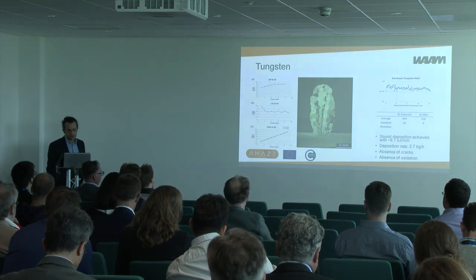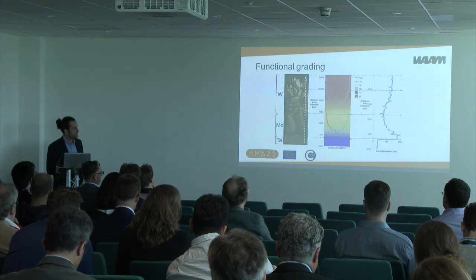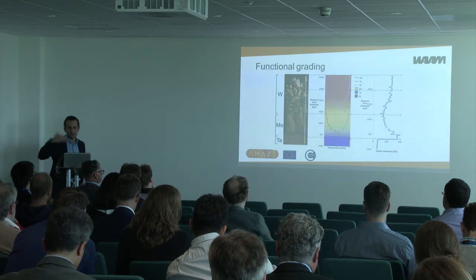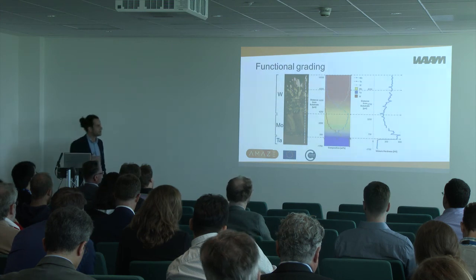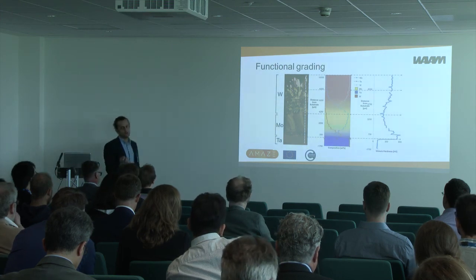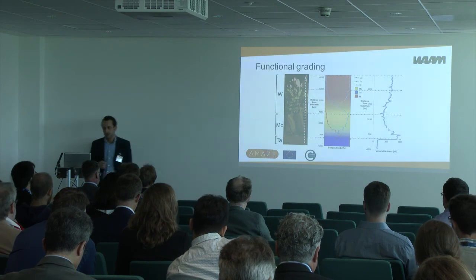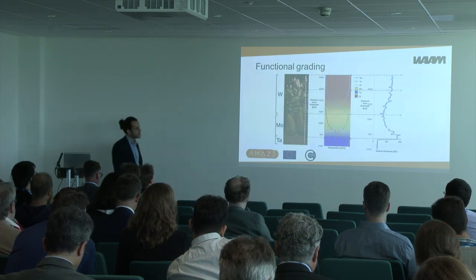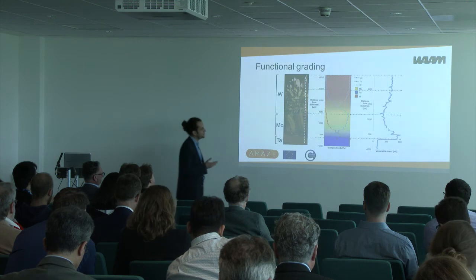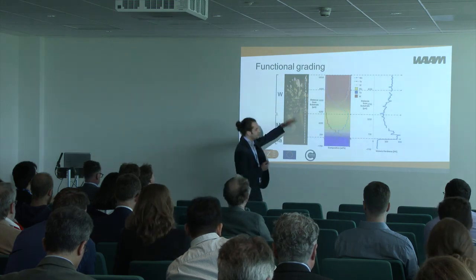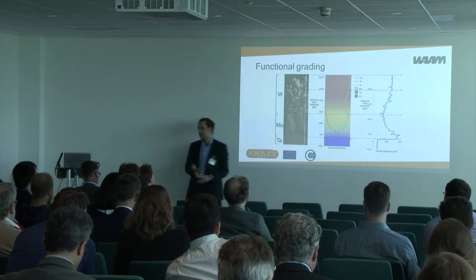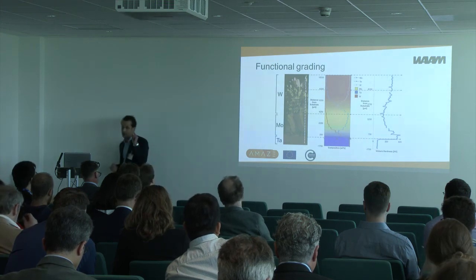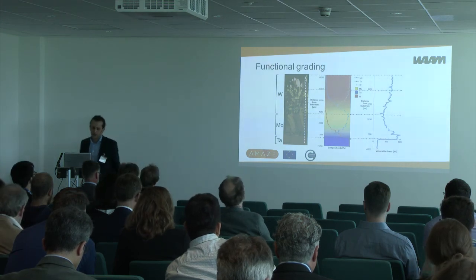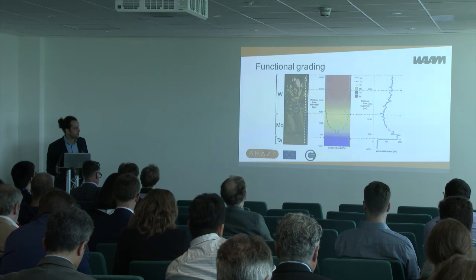Then one of the requirements from the Center for Nuclear Fusion was to have a graded structure which had tungsten on the top to face the radiation coming from the core of the reactor, and then the underlying structure had to be made of molybdenum to give mechanical strength. And we were able to achieve a very nice gradient. Unfortunately, it happens over 4 millimeters of length, and the requirements coming from CCFE were actually for a 1 millimeter graded structure. So we're going to do some optimization of the parameters to see if we can get there.